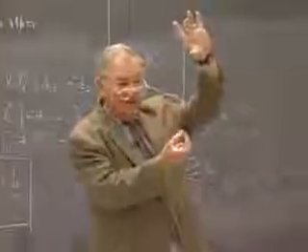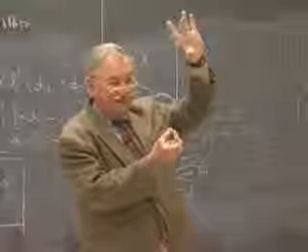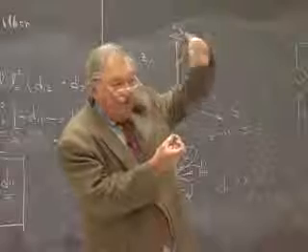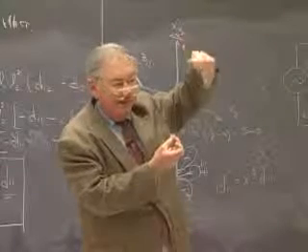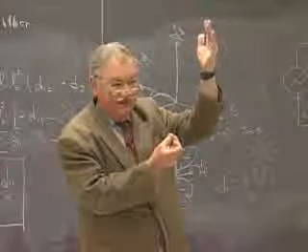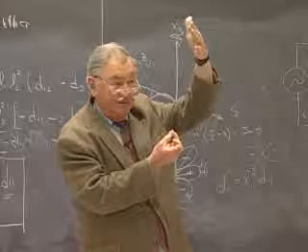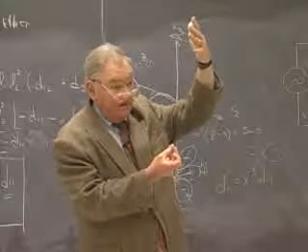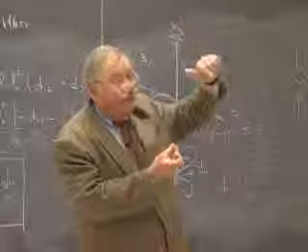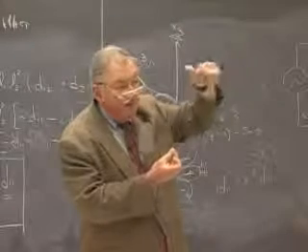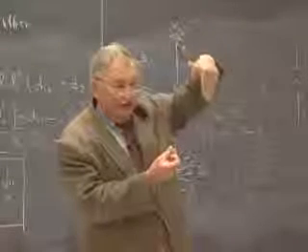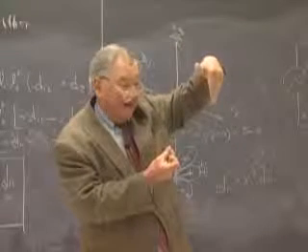If you hang the weight on the crystal and it's a flat plate, how would you orient the crystal to get the optimum sensitivity? So you define a scalar modulus for the crystal and the particular direction you're exerting a uniaxial stress, and then you express this modulus in terms of theta, the angle of rotation within the crystallographic plane.